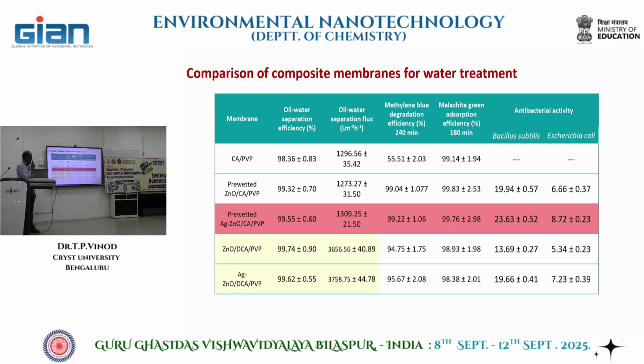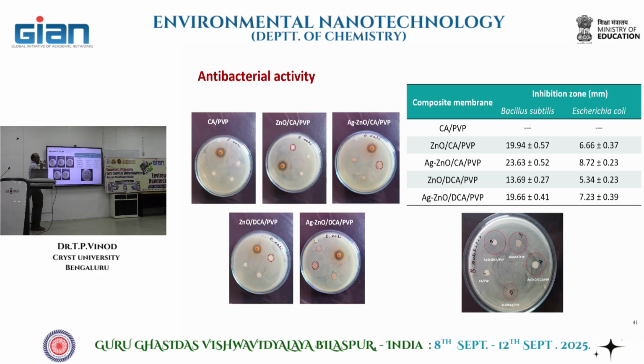Okay, then one more application we looked for. We took pieces of this membrane and kept it in some bacterial growth media. We could see the inhibition of bacterial growth wherever you have this material. It's again because of the presence of the silver-doped zinc oxide we used. That silver is actually giving the antibacterial property. That's the major contributor, and zinc oxide to some extent is also contributing to that property.